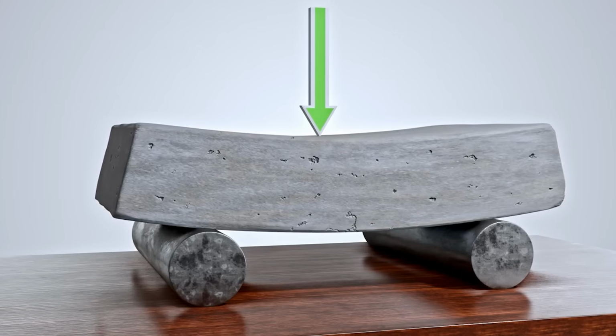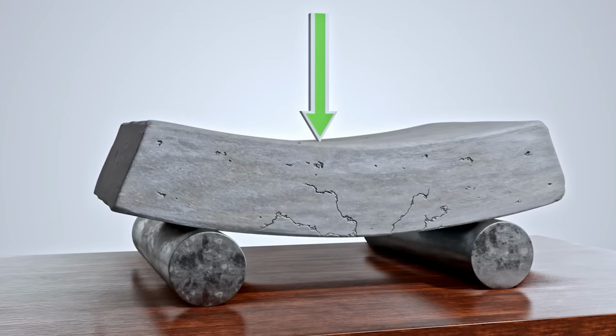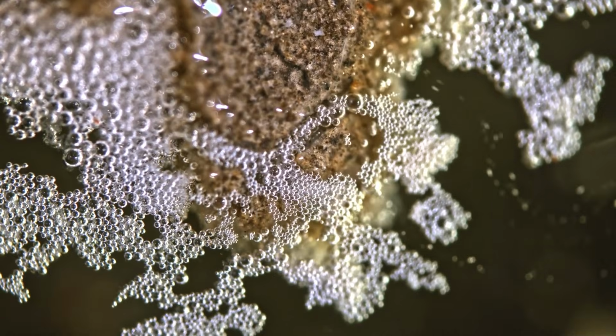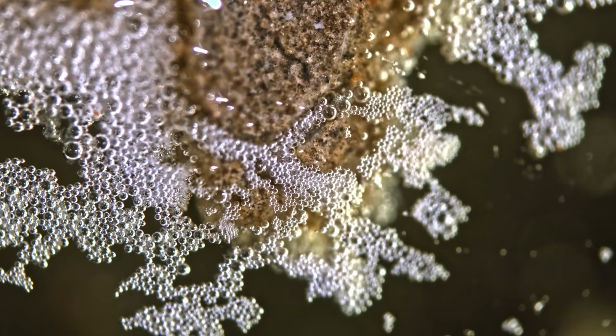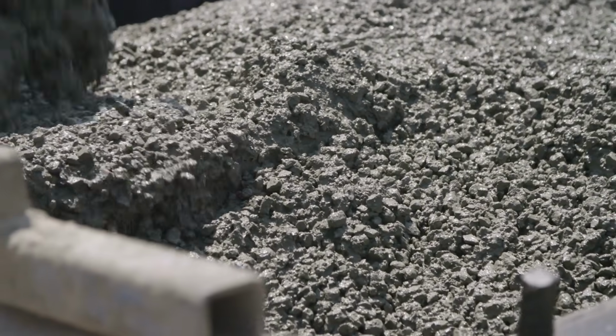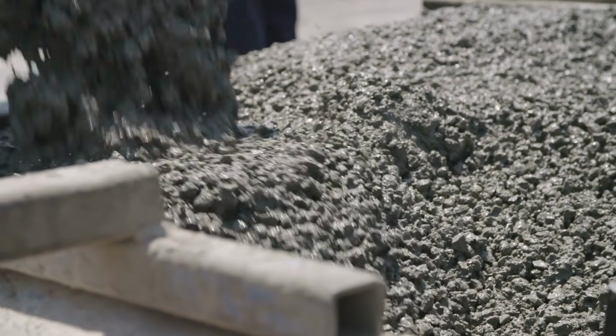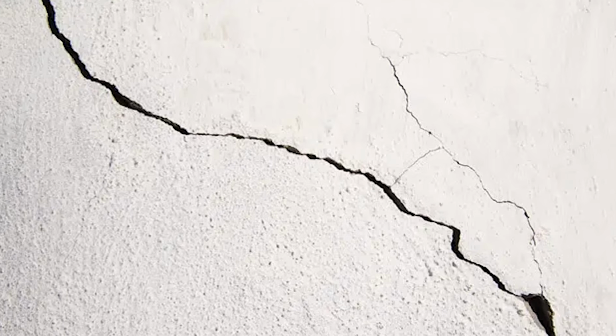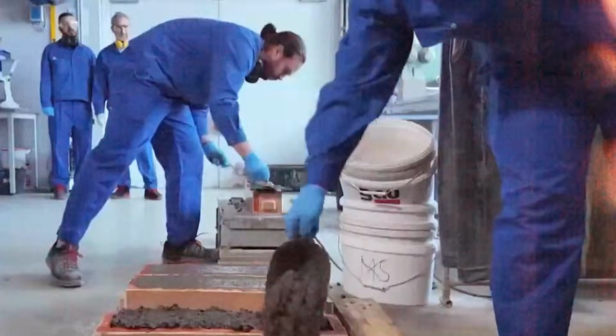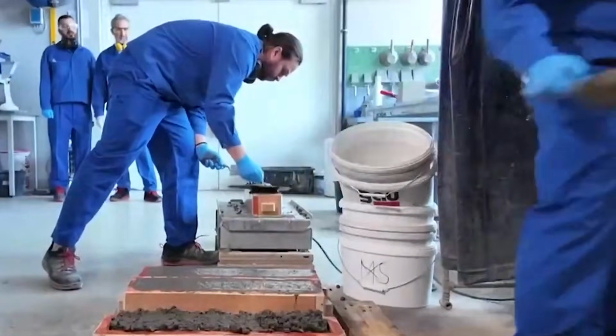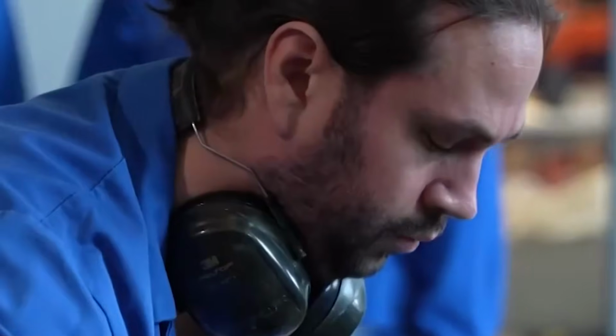it is dramatic. And critically, the biggest improvement often shows up in the weakest part of the whole material, the microscopic zone where the cement paste wraps around each stone. In ordinary concrete, that boundary is the flimsiest link in the chain, the first place a crack appears under stress. Under compression, it tightens up hard, and the weakest link becomes far stronger.